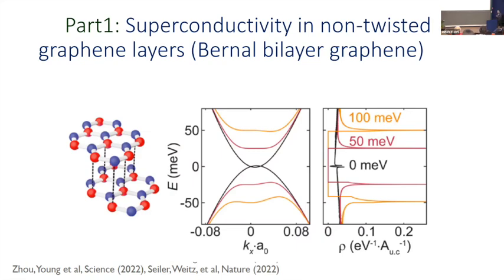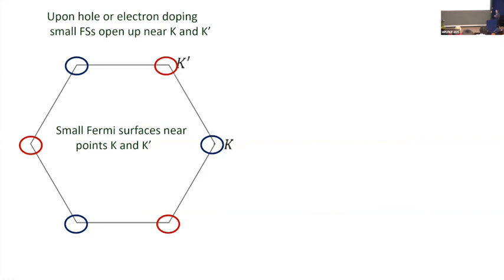The new element is that when you apply an electric field — called a displacement field — you essentially start splitting excitations in the two layers in a very intelligent way. The excitations get split, there is a gap, but there is a very flat top and very flat bottom of this dispersion, creating flat regions. By no means a flat band — the bandwidth is finite — but there are regions where excitations are almost completely flat.